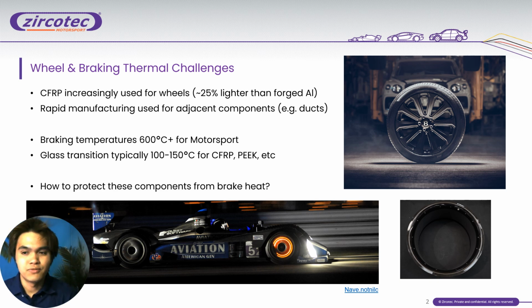The carbon fiber wheel would only withstand around 100 to 150 degrees, depending on the resin that is used, and for plastics you would expect, even for a high temperature plastic, 100 to 150 degrees. This means the radiant heat from braking would lead to deformation and structural damage to anything plastic within the wheel. So how do we prevent this from happening? It is with our thermal barrier coatings.